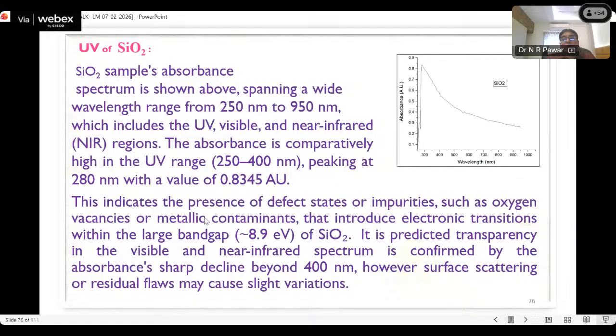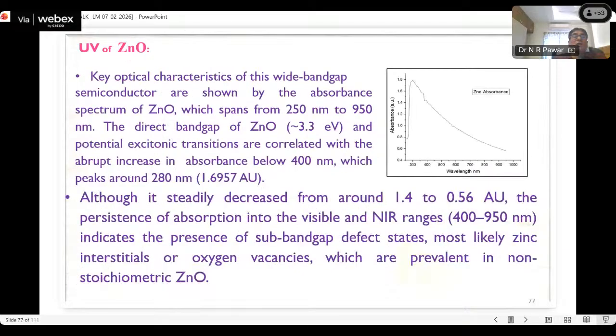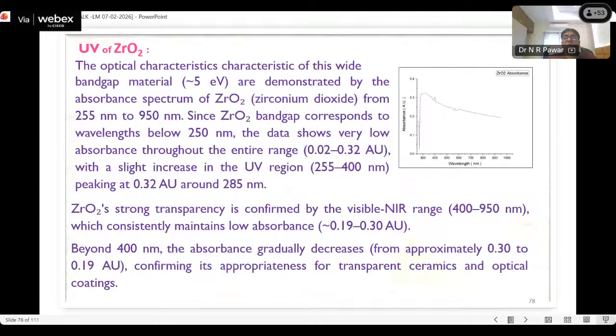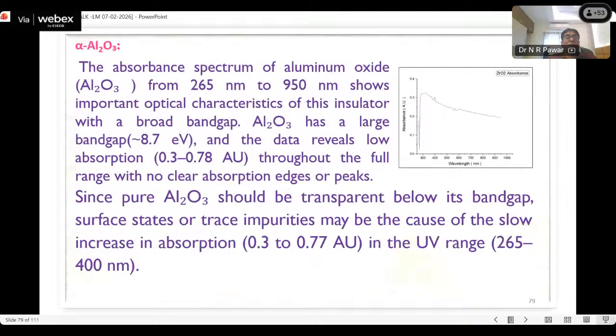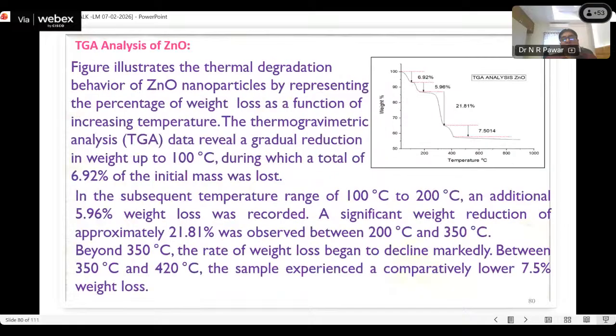This indicates the presence of defect states or impurities such as oxygen vacancies or metallic contaminants that introduce electronic transitions within the large band gap of this SiO2. The predicted transparency in the visible and near infrared spectrum is confirmed by the absorbance's sharp decline beyond 400 nanometer. However, surface scattering or residual flaws may cause slight variations. And this is the UV of this ZnO. This is the UV of ZrO2, UV of alpha alumina, and TG analysis.